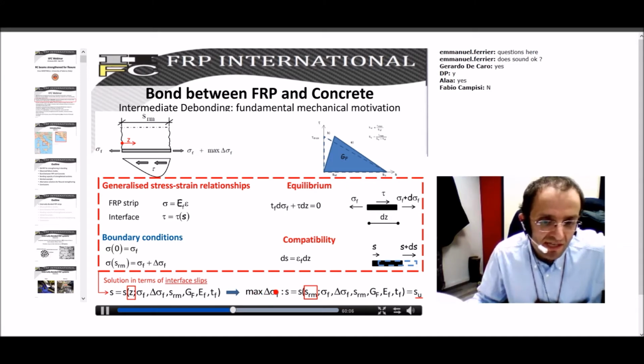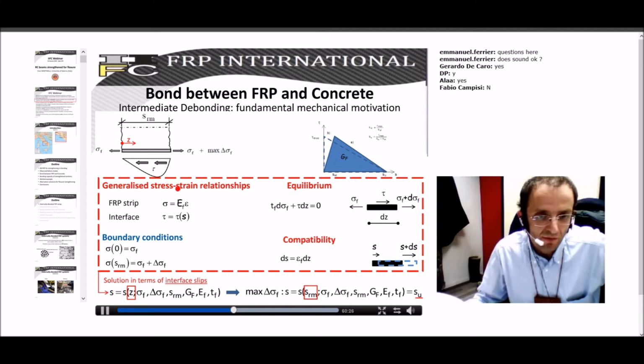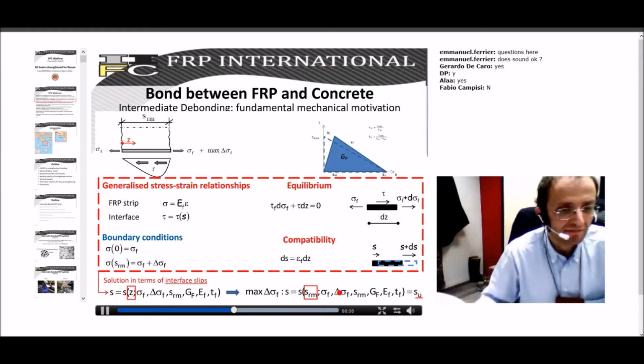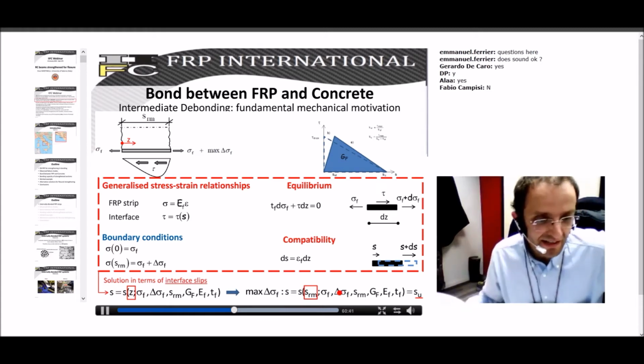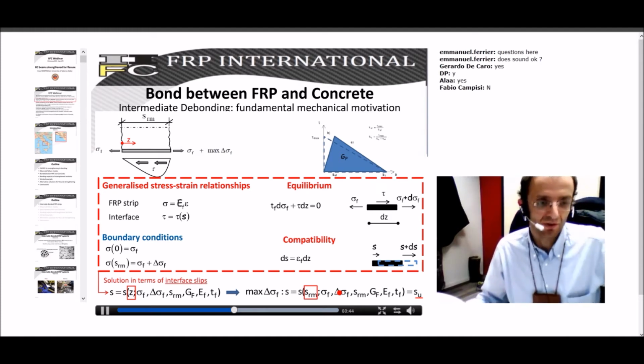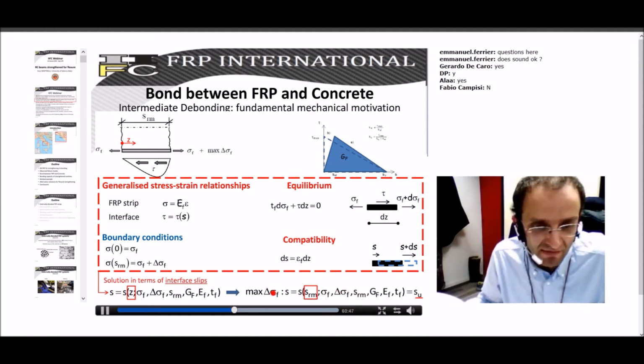You can also evaluate the maximum delta sigma, because the maximum delta sigma is the value of delta sigma for which S evaluated at the end of this segment, for z equal to S_rm, is equal to S_u. So you evaluate the maximum delta sigma resulting in attaining here S_u, ultimate, depending on your solution. So if you have all the values of S, you evaluate S at the end of this segment, and you impose here that this value is S_u. This is the incipient debonding condition. And this is the way in which one can evaluate the maximum delta sigma.